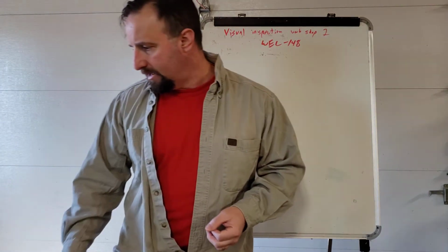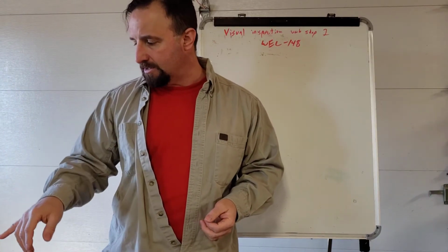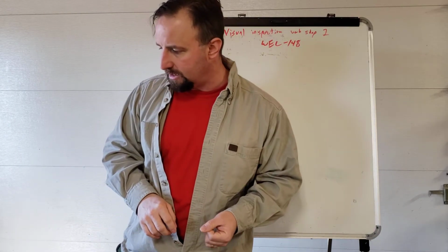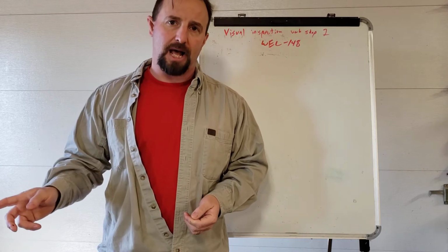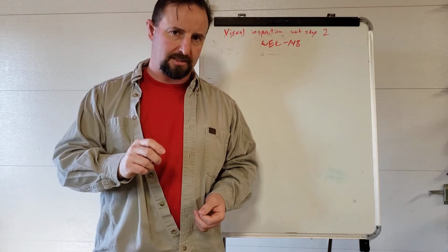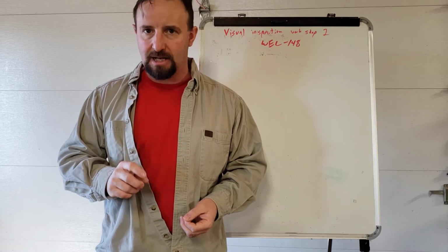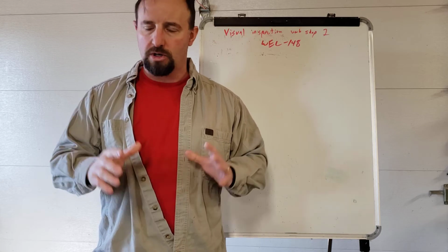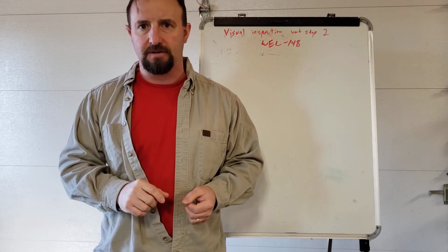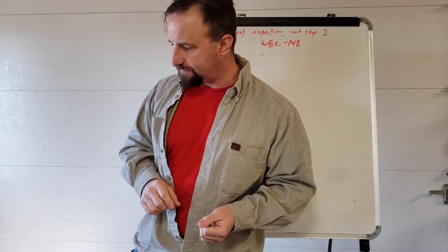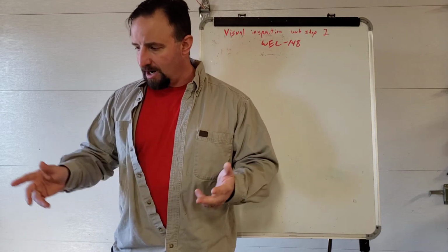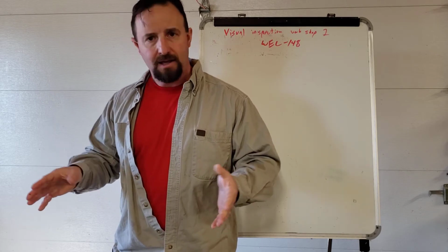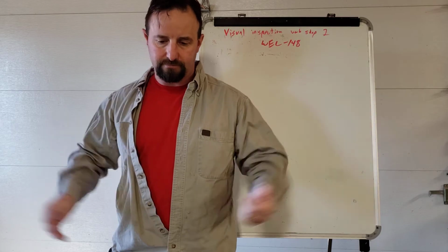So, next slide. This is incomplete fusion. The slide you should be looking at says figure 2.6, incomplete fusion. This is actually a plasma arc weld. What a plasma arc weld is, is kind of like a TIG weld, except instead of having an electrical arc, it's got a plasma jet in there. And it works wonderful for stainless steel, especially relatively thin stainless steel. But right here, they just missed. And so he was off to one side, and two sides didn't melt together. Yep, incomplete fusion.